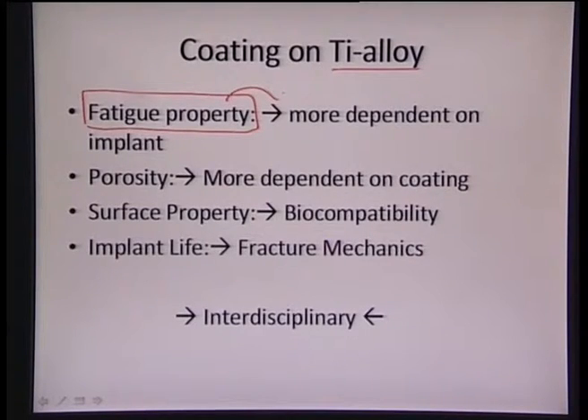So that part we can see that fatigue property is more dependent on the implant, or the titanium alloy which forms the implant, and to improve the fatigue property, it is only the titanium alloy which is responsible here. So we need to perform certain heat treatments, as we saw earlier, a controlled heat treatment. We have to take the material below 1000 degrees centigrade and do the heat treatment. So the yield strength and the fatigue strength increase to a large extent in comparison to the titanium itself.